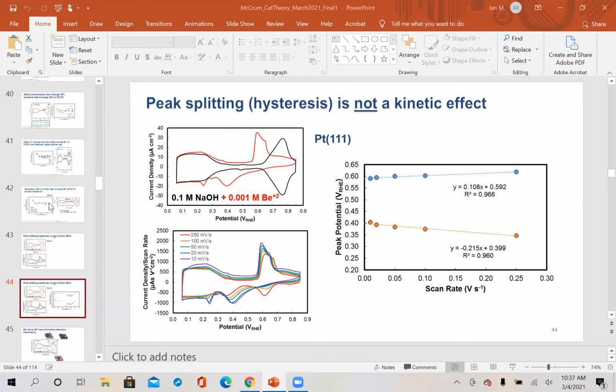I'll maybe briefly mention, we did look at this a little bit on the step edge. And the hydroxide does not have to be close to the cation on the step to still see this weakening effect. But I think that's complicated because we get this long range hydrogen bonded structure of OH and water on the step. And so really what we're seeing is that if the cation is adsorbed anywhere along the step and it disrupts that water, it's going to alter this long range hydrogen bonded structure and alter the binding strength of OH and water. And so yes, maybe it's a little bit weaker, but it still is fairly long range because the hydrogen bonding distributes the effect of the cation. And so we'd have to do a more careful study of, okay, let's just use a local OH water structure and then move the cation around and see what effect that has. Okay, no, that's really interesting.